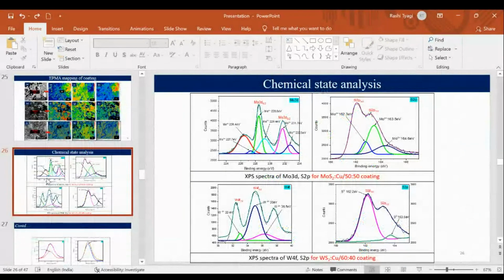The chemical state analysis was checked by using XPS analysis. XPS is performed to check the chemical state or bonding state of the solid lubricant. Initially, I told you that solid lubricant can dissociate into different compounds, and if they dissociate you cannot get the complete tribological properties from the solid lubricant. So we have done the chemical state analysis, X-ray photoelectron spectroscopy, to check if there is a good bonding state between its elements.